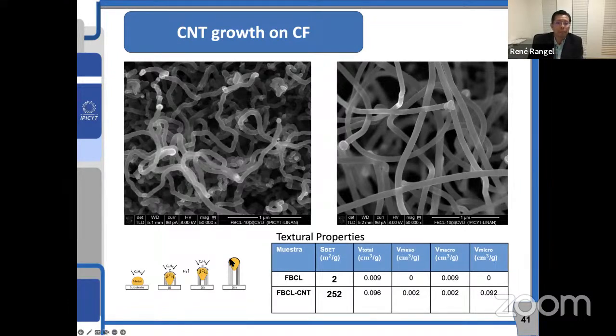As you can see here in the tips, the catalyst is at the tip, okay? And here, something very important is that the aim is to increase the surface area drastically. The natural fiber, the carbonized fiber, has a very low surface area, close to 2 square meters per gram. But once we grow carbon nanotubes, the surface area increases up to 250 square meters per gram. This is very important because all this area is already exposed to absorb CO2, okay?